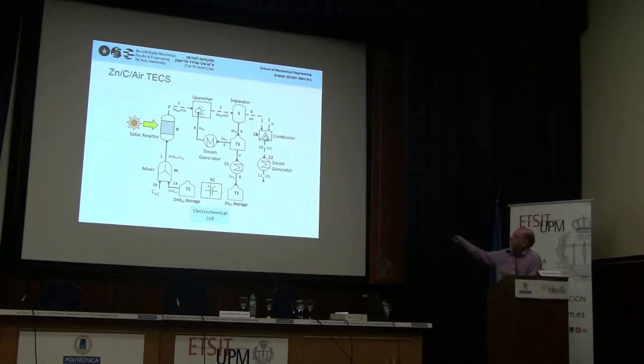After we have that, we can separate. We have the liquid zinc, and then we can solidify and store the zinc as a powder at room temperature indefinitely until it is needed. We also have an interesting byproduct, which is CO coming out of the system. In principle, we can, for example, combust the CO, get CO2, and extract the thermal energy that is embodied by the CO and make steam or make electricity, something that can be useful.